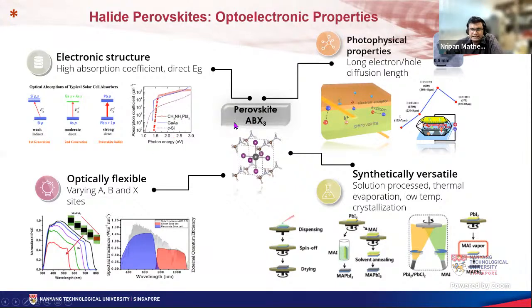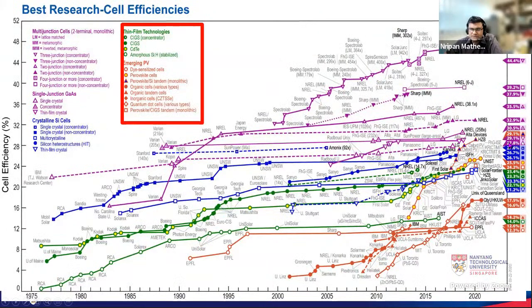And by substituting the A and the X, you can change the band gap. Over here, if it is the iodide halogen, then the absorption edge is at 800. But if you substitute the iodine with bromine, you can see that the band gap can be changed as well, and you can have more or less continuous variations in the band gap within the system. The processability as well as the electronic properties is why a lot of people work on it for solar cells. The efficiencies of these solar cells are very high, comparable to silicon, although perovskite is still very young, and the sizes in which these solar cells are shown are very small.